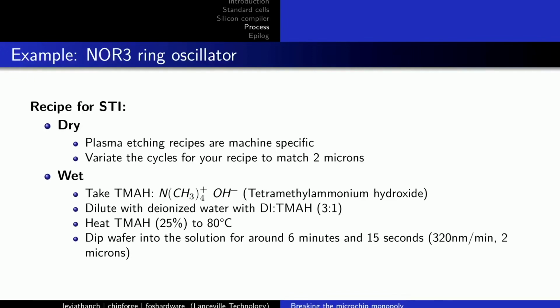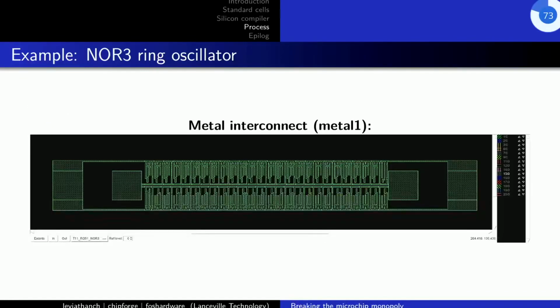The recipe is pretty easy. Either you have a plasma etcher around, or if you are not rich and don't have money to buy a plasma etcher from eBay, you can also get tetramethylammonium hydroxide. And it's not even a German name, a word, so cool. Dilute it with deionized water, 3:1, with this 25% TMAH solution. You heat it up to 80 degrees Celsius, dip your wafer for 6 minutes, and then you get your structures.